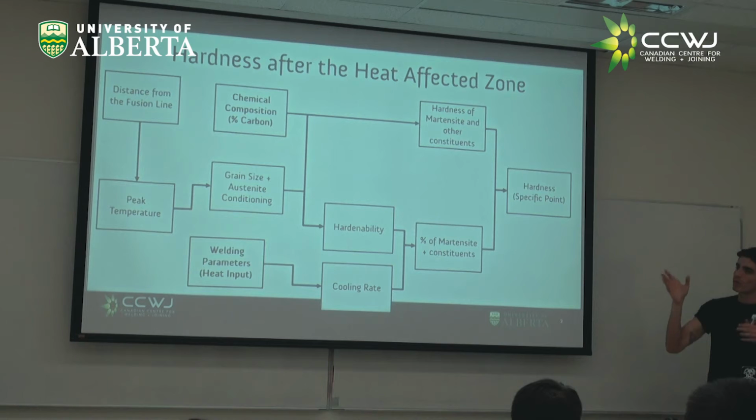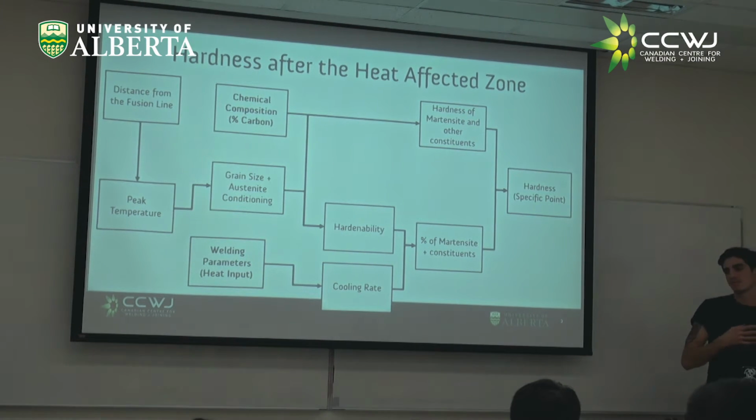But when it comes to welding, it's a complex heat treatment. It's a rapid heat treatment. So we can apply the same kind of thinking, right? And think, okay, at my specific point, the hardness will depend on how much martensite and how hard the martensite is. So let's go with the easy one. How hard is the martensite?